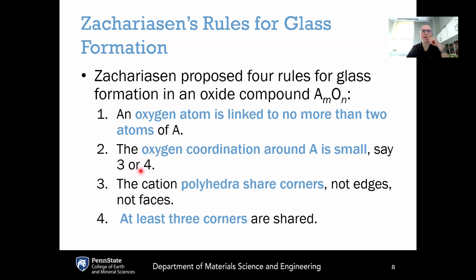It's 3 or 4 because the glass network needs to be able to build a random network in 3 dimensions. If we're living in a 3-dimensional space and we need to be able to make a glass that occupies this 3-dimensional space, that means that the glass structure must form this 3-dimensional network, which means that we have to be able to have rigidity in the network across those 3 dimensions.